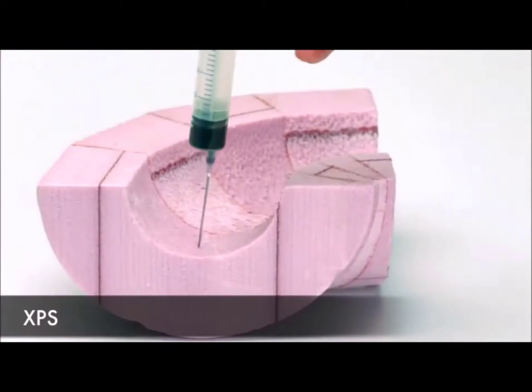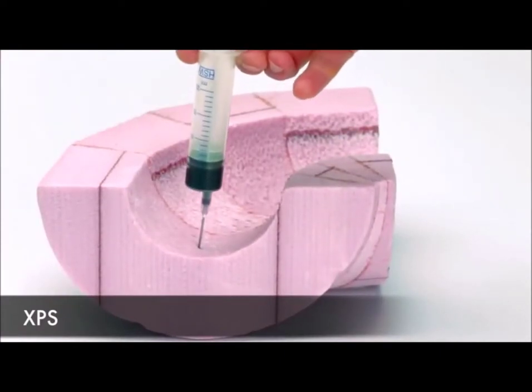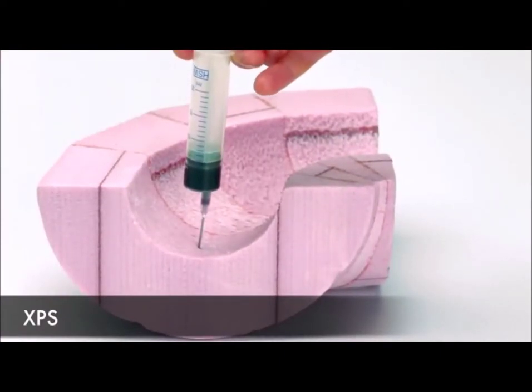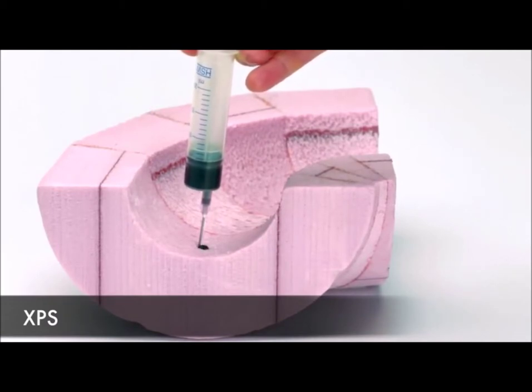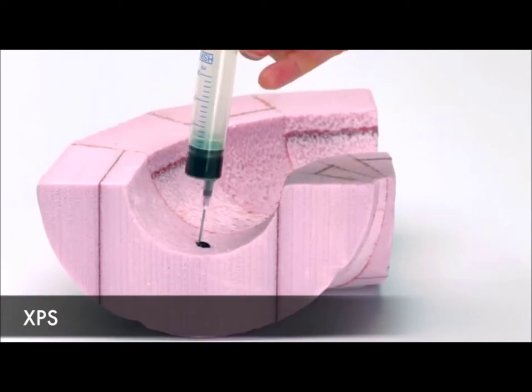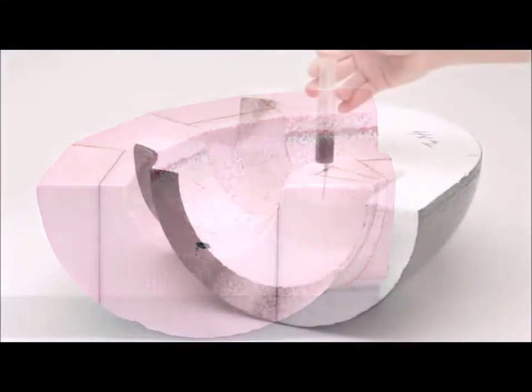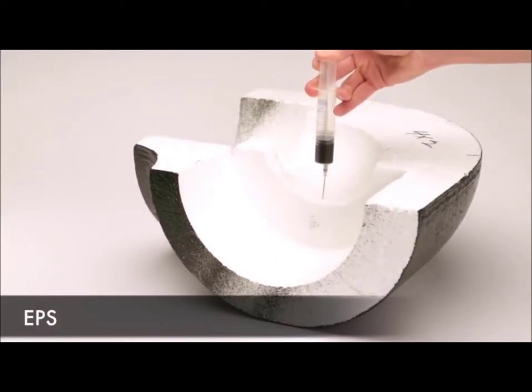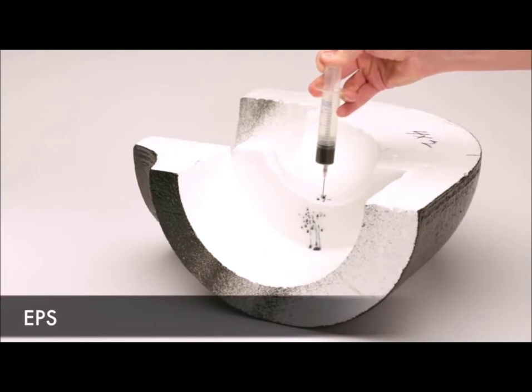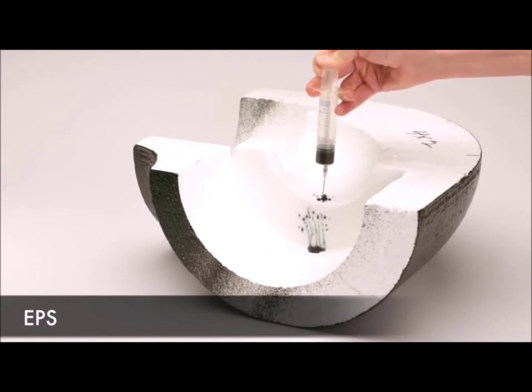In higher density EPS products, the fusion of individual beads is better than lower density EPS products, but the problem still exists. Foamular XPS features 0.3% water absorption by volume across all ASTM types, meaning potential to absorb is very unlikely. Now EPS features 2-4% water absorption by volume across all ASTM types, meaning EPS potential to absorb is 10 times greater than Foamular XPS.